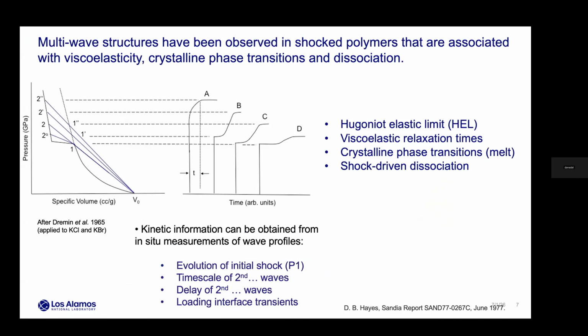I want to give a little bit of discussion about how these features that I mentioned at the beginning give rise to evolution of shockwave profiles. Anytime you have a volume discontinuity or some sort of evolution due to viscoelasticity, you end up getting wave evolution. And so this really is just to point out that the propagated shock waves give you a lot of information about timescales, volume changes across transitions, and kinetics. So I show this for a phase transition. This would be a densification transition.